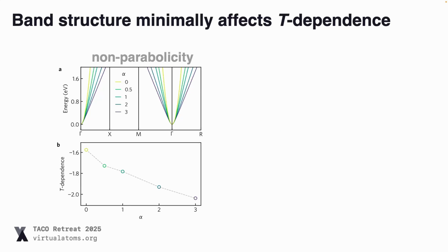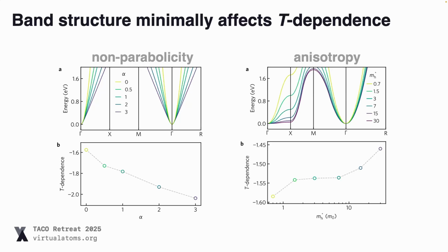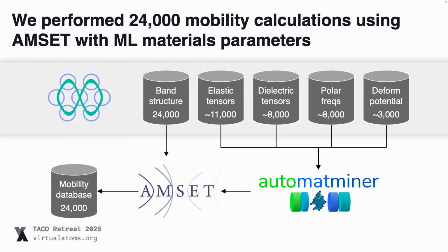We also looked at other things like non-parabolicity, so linear bands away from the band edges, and also anisotropy. And we found that these do modulate the temperature dependence, but nowhere near as much as the phonon frequencies. The final thing we wanted to do is, again, these have all been model materials, so we wanted to have a look at more realistic band structures. And so we generated a data set of 24,000 mobility calculations using AMSET. Now, I mentioned before that we need all of these materials parameters, so we needed to obtain them all for the materials of interest. To do that, we just used some machine learning. We took all of the elastic tensors, dielectric tensors, and phonon properties from the Materials Project, trained machine learning models on these, and then fed that along with the raw band structure into AMSET to obtain our mobilities.